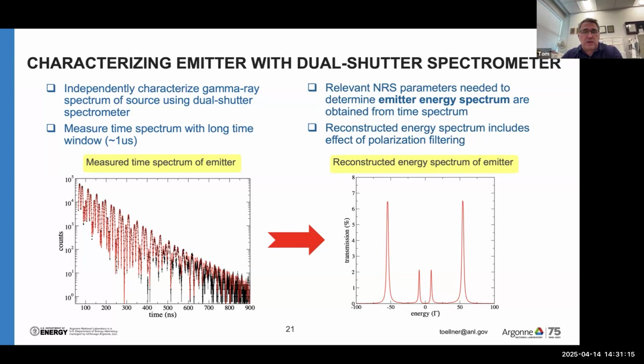You see it kind of breaks down after about 400 nanoseconds, and that's because the iron foil was not completely magnetized. So the magnetization field should be stronger. But the impact on the energy spectrum is pretty minimal. For the new instrument, I will have a stronger magnetic field so I can saturate the magnetization and make it more clear exactly what the spectrum is. And then when one introduces polarization optics, one arrives at the 4-line spectrum shown on the right. You get all the hyperfine parameters you need from the time spectrum, then you generate the energy spectrum.